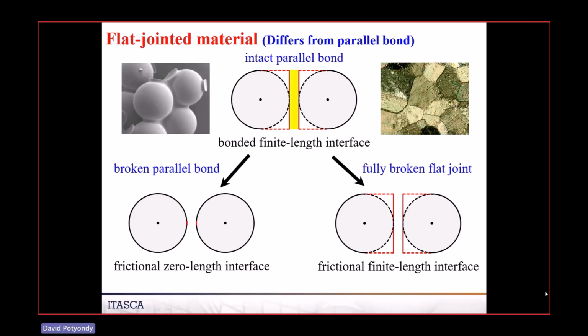When you have these remaining interfaces that you get with a flat joint, you calibrate to the direct tension test, and it's the micro tensile strength that governs that, so you choose the micro tensile strength again. But then when you start to do a UCS test, you don't get this localization. You just get partial breakage of tensile cracks all throughout the system. And then in order for the thing to fail, there has to be some localization where these things participate so that you can get an axial split or a shear fracture that spans the specimen. That process of localization requires a small number of micro shear failures to link these things up.